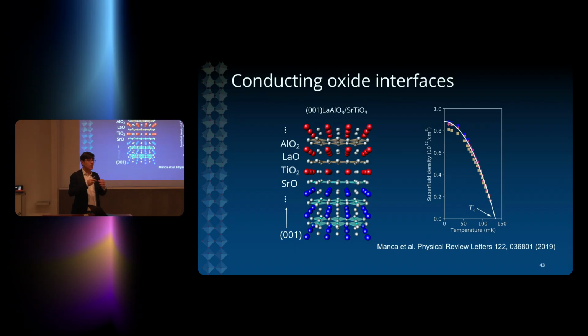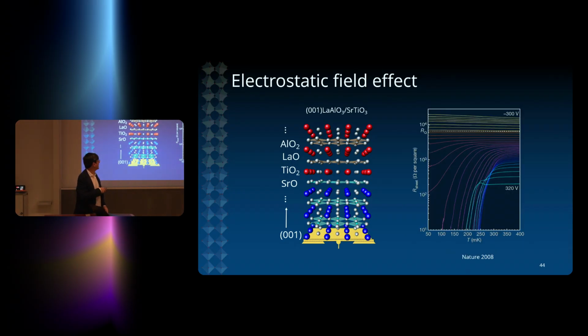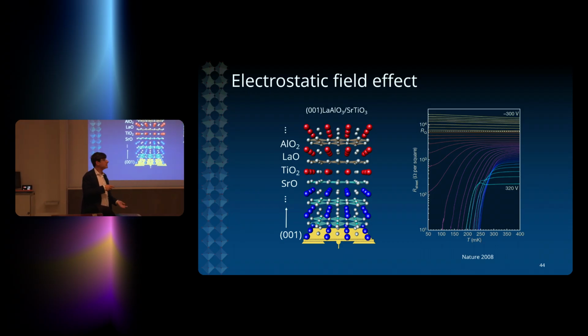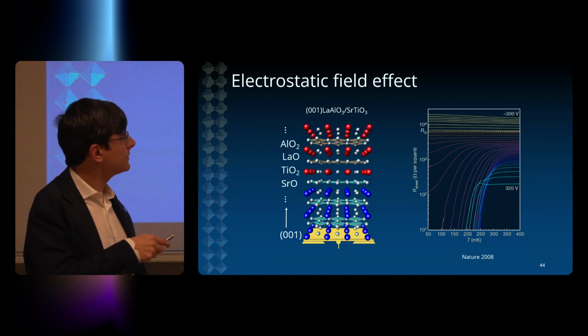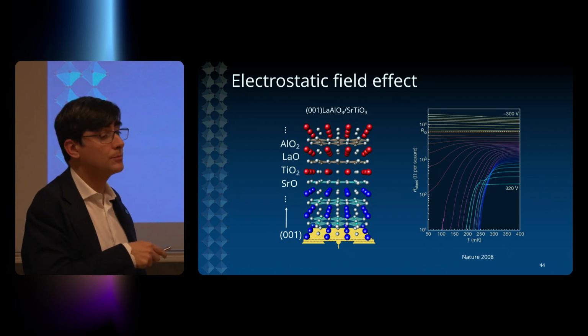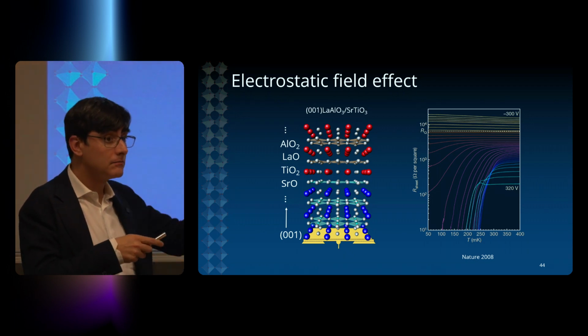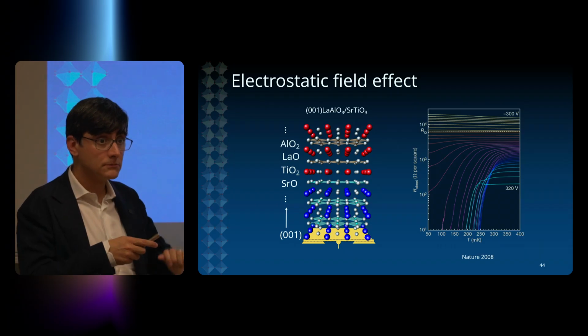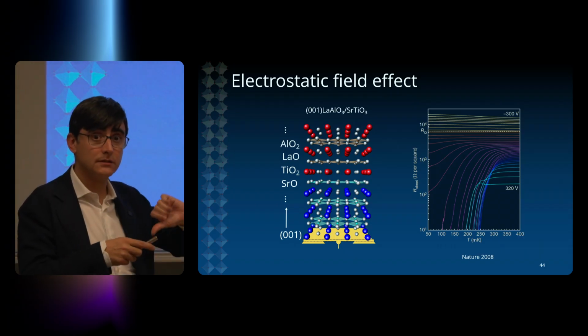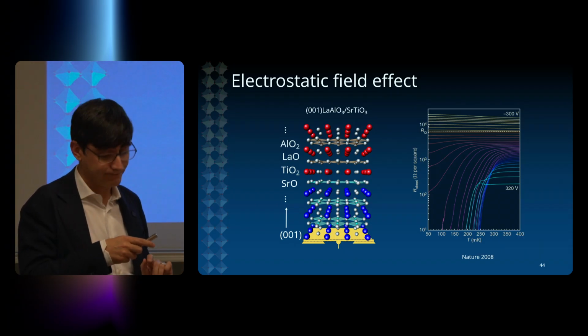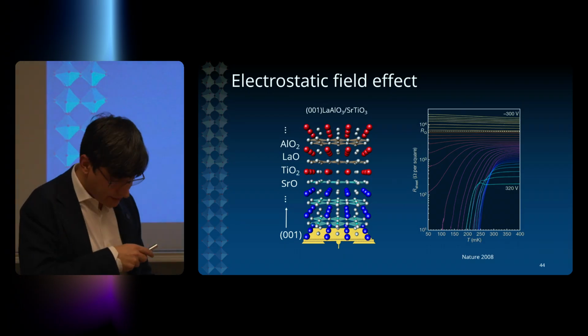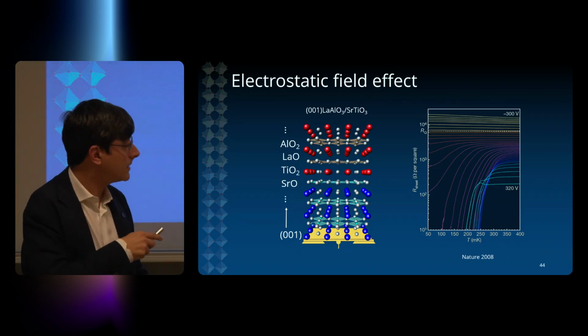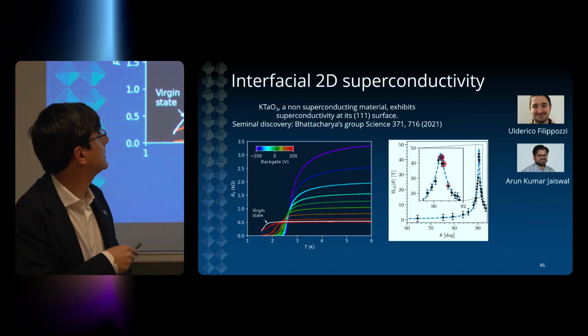Because the superconductor is so dilute, you can apply a gate voltage, like in a field effect transistor, and switch superconductivity on and off. You can increase or decrease the number of carriers in the system, move the position of the chemical potential, change the mobility of the electrons, and go through an insulator to superconductor transition with a switch. You go from zero resistance to a finite resistance by flipping a switch. That's another interesting property that you get especially at this interface.